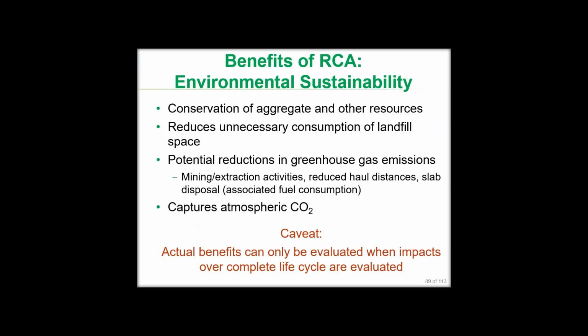There's a recapture, if you will, of atmospheric carbon dioxide by the exposed concrete through a process called carbonation, where carbon dioxide is absorbed back into and is chemically combined with the calcium hydroxide to form basically more calcium carbonate in the aggregate itself, hardening the outside of the aggregate. So a lot of potential benefits, and again, as was mentioned previously, the actual benefits in any specific case need to be evaluated in the context of that particular project over its life cycle.